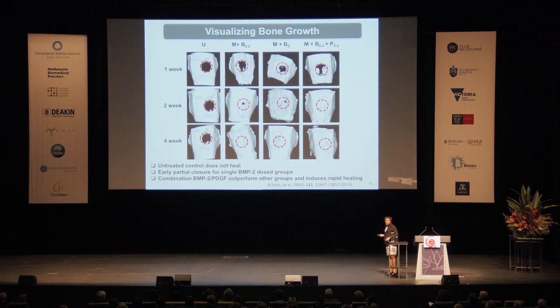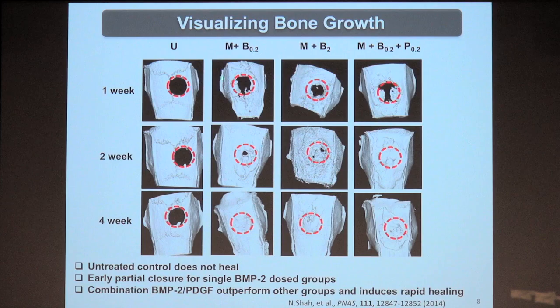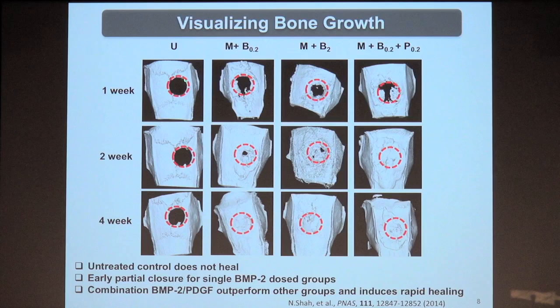When we do these studies, we use a cranial defect model. So these are rats which have a cranial defect. This is the control, and as you can see, if you look over time, in the micro CT, which is a kind of x-ray, there's no healing of this bone. If we put our patch with our layer-by-layer film in place of this defect, we can see at different doses, at 0.2 micrograms of BMP2, that we're getting already very rapid healing and replacement of bone.